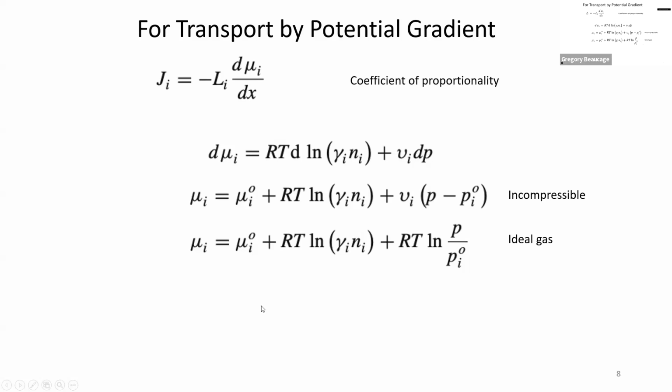So this is the idea: if you want to be a membrane scientist, then you have to have an equation that governs all membranes, both porous and non-porous. It turns out the chemical potential will do that for you. Because it's got the pressure gradient one, it's also got the concentration gradient one, Fick's law.